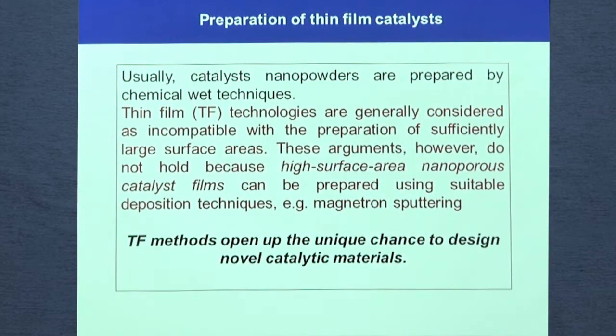Okay, so what I'm going to show here is the preparation of thin film catalysts. This is, as I already said, quite unusual, because typically catalysts are nanopowders prepared by chemical wet techniques, and thin film technology is generally considered incompatible with the preparation of large surface area, because thin films are typically flat and non-porous. However, if we are able to prepare, by using some special deposition parameters, a high surface area, and if we are able to produce by thin film technology a nanoporous catalyst film, we can profit from all the possibilities of thin film technology.